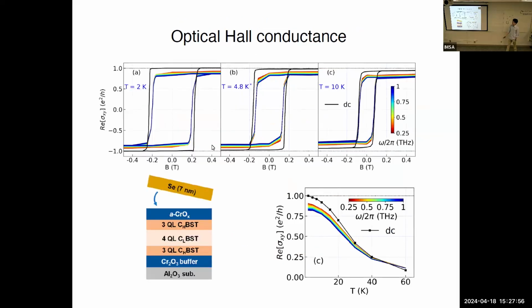And that's what we did here. Here I show the optical conductances measured at three different temperatures: 2 Kelvin, 5 Kelvin, and 10 Kelvin. And these are the hysteresis loops. The black lines show the DC data from the earlier work, and the color data shows the frequency response at different frequencies from 0.25 to basically 1 terahertz.